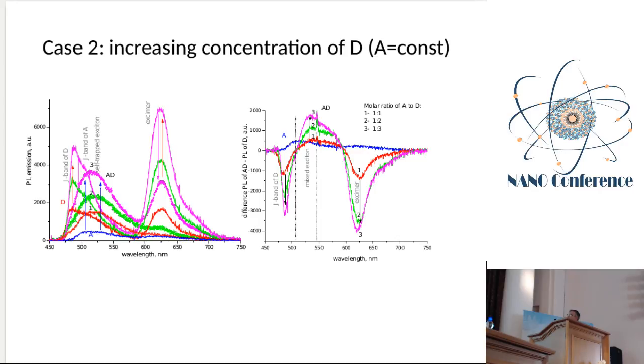Again, here we have a rapid decrease of J aggregate emission of the donor. So because they provide energy for the mixed solution for the acceptors, and we see the decreased contribution of the excimer, and we see again the increase of energy at the wavelengths of approximately 530 nanometers, which again doesn't correspond neither to J aggregates or dimers of J aggregates in the solution.